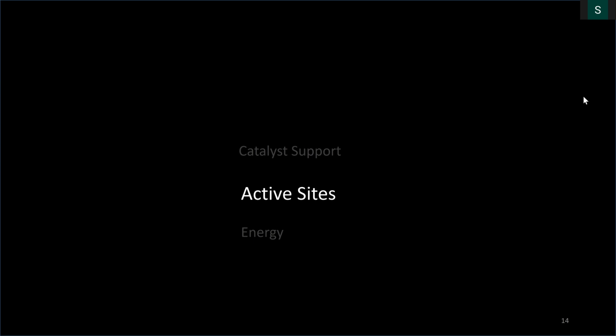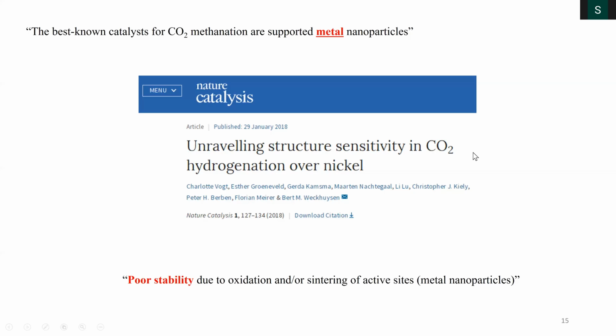If you look at the literature, the best active site is the metal nanoparticles. This is one of the best examples by Bert Weckhuysen, where they use nickel nanoparticles supported on silica for CO2 hydrogenation to get methane. But the problem with metal nanoparticles is that they are reactive but also very unstable, because nickel 0 can oxidize to nickel 2 or 3 or plus 1. Because of this oxidation, nickel is no more active. These nanoparticles then also undergo sintering, and the particle size grows. That also reduces the catalytic activity, and within a few hours the catalyst dies.